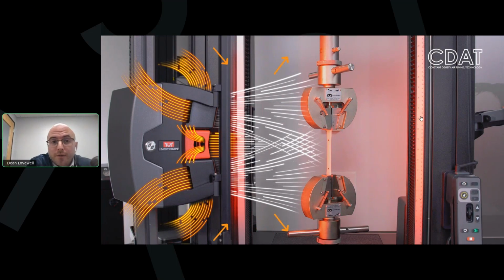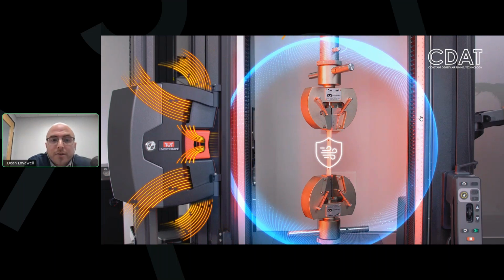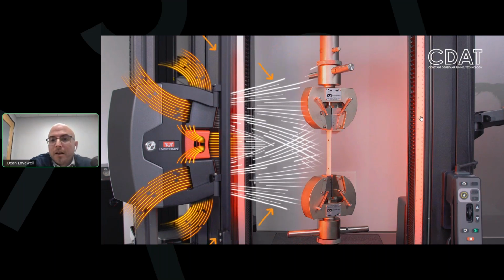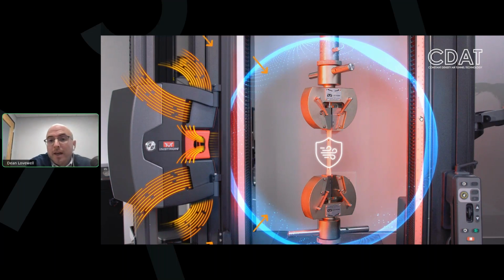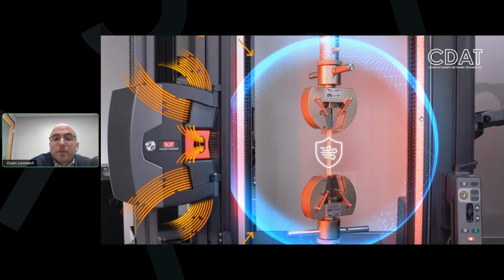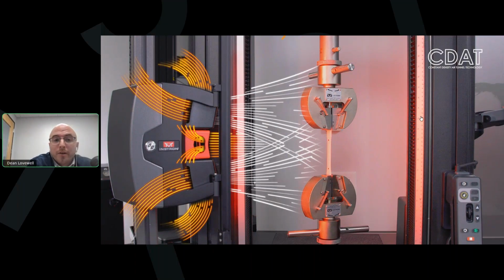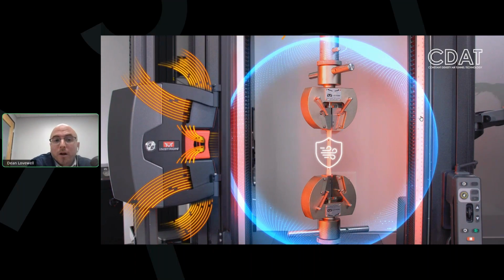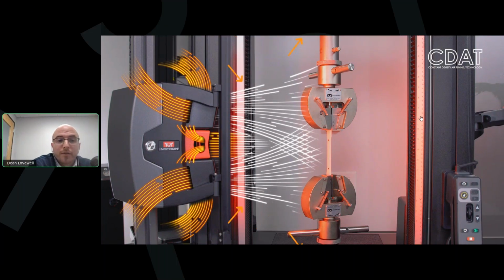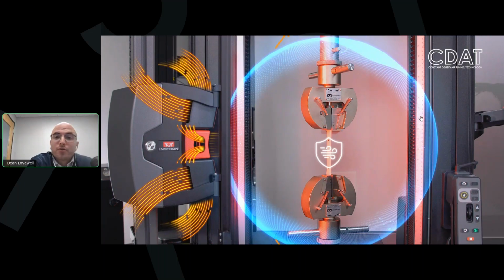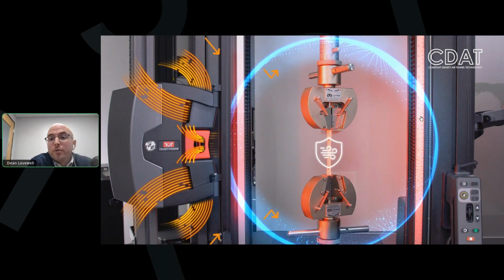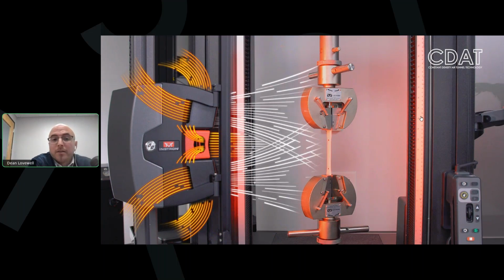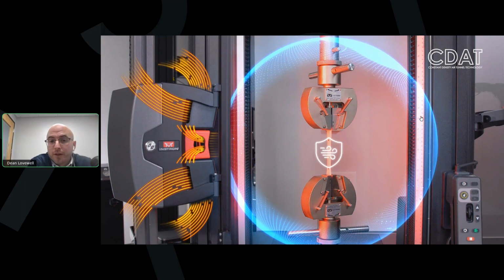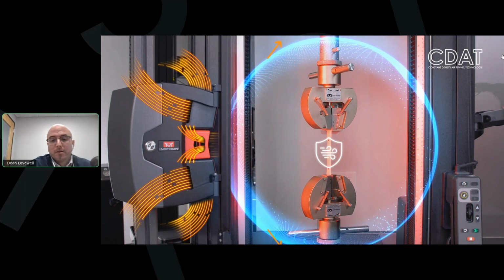Now, another great advantage of using the AVE3 technology is that you also gain the advantage of the environmental conditioning capability included in the AVE3 extensometer. This extensometer uses Instron's proprietary technology called CDATs, or constant density air tunnels, to control the airflow between the camera and the specimen. By controlling this airflow, we're able to reduce the noise in your strain data, delivering the most reliable, repeatable strain data for a video extensometer.